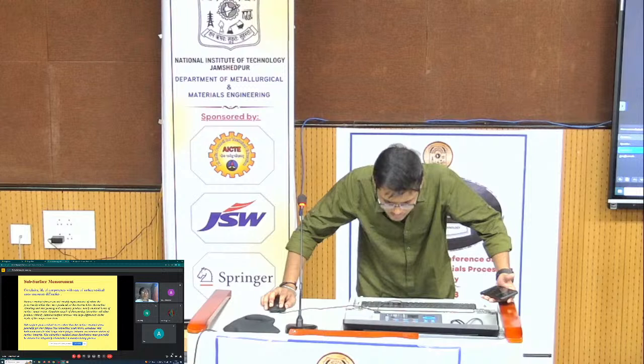And when you go to subsurface, you remove the top surface, not by mechanical polishing, actually by electrolytic polishing. And each layer that you remove, thickness that you remove, there is an equation that gives you the modification. And we started doing this for our gears also, which we are supplying to Renault Nissan, day in and day out in Pune. Now this is what we do. The shot peening, I told you, after the carburizing and shot peening.